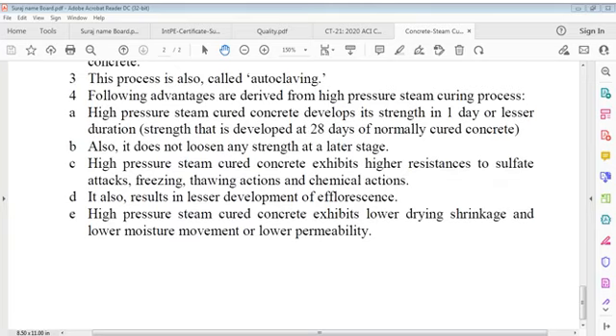The advantage is in curing time. High pressure steam cured concrete develops its strength in 1 day as it could in 28 days. Also, it does not lose any strength at a later stage. High pressure steam cured concrete exhibits higher resistance to sulfate attacks, freezing and thawing reactions, and chemical reactions.